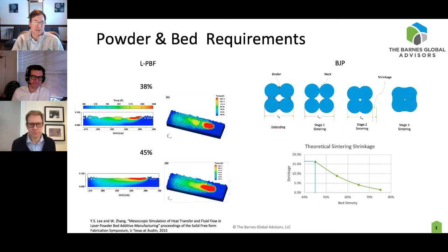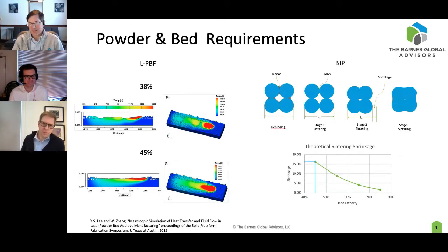use fine powder, right? So from my history working with tungsten, we were using 1 micron tungsten powder in order to be able to sinter to 95, 97% density, and that didn't flow. The molybdenum powder that I used to use in a past life was the same. You could put it in a hopper with a 6-inch opening, and it would bridge the opening and stop flowing. Those sorts of things are really tough as you try to get something that solves a sintering problem.